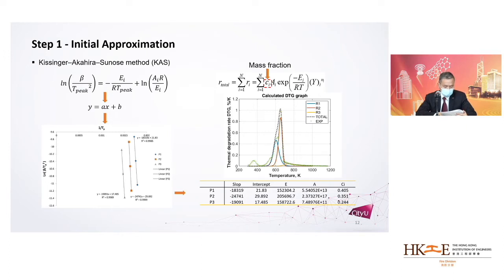Now, this approach was proposed firstly by Kissinger, Akahira, and Sunose. We call it the KAS approach. This is a very conventional approach that will help us to identify the pyrolysis kinetics for various components of a composite material. If you look at the graph on the right-hand side, you will see a typical result of a composite material undergoing thermal TGA analysis. You can see that the experimental curve resulted in a number of peaks, roughly 3 peaks. Therefore, there should be 3 parallel or sequential pyrolysis reactions going on in this composite material.